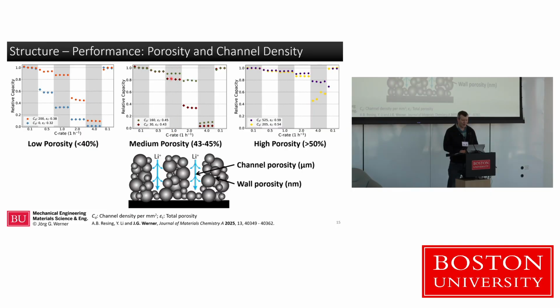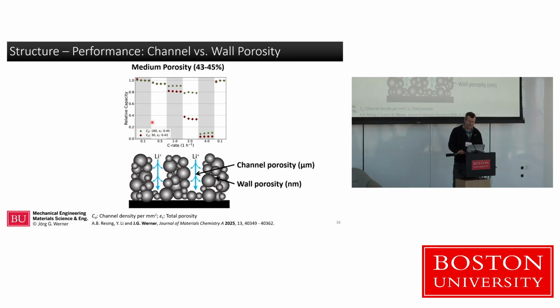And we see that at a 1C, so 1 hour charge, they pretty much behave very similar, 80 to 90% capacity we can get. And then we accelerate it to twice that rate. One goes below 40%, the other one stays at 80%, right? So just from 30 to 160 channels per square millimeter makes such a big difference. And I want to emphasize here that the difference is really just, is the porosity in these channels, or do you have porosity in the interparticle space, in the walls we call them, right? Because the overall porosity is the same here. So contributing some of the porosity into the channels can really make quite a difference.